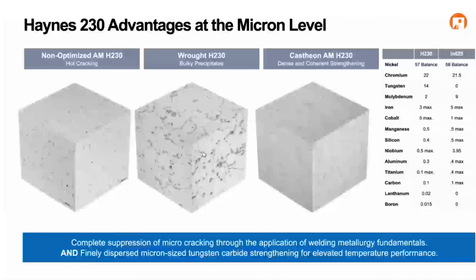I wanted to talk a little bit more about the microstructure. If you look in literature, some folks have worked on Haynes 230, and it can, from a robustness standpoint, have hot cracking issues and microfissuring, which of course would degrade your properties quite a bit and is unacceptable. But when you pick the right chemistry, you're actually able to mitigate these issues, as you can see here on the right-hand side.